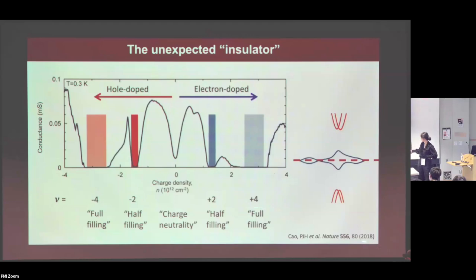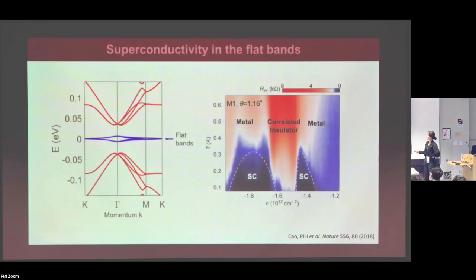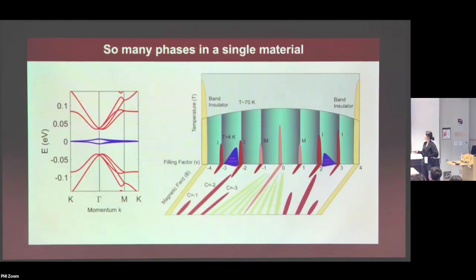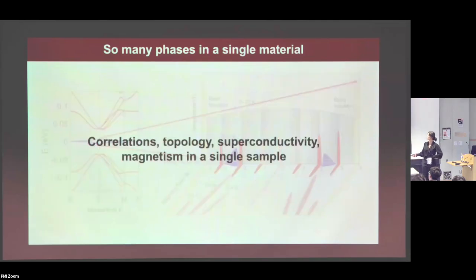But the surprising thing that happened in 2018 was that even when you just half fill this band, where there's no band insulator, you still have this suppressed conductivity, which is the correlated insulator, the insulator gap formed by the strong interactions between the electrons in the flat bands. And in the same material, as you've already heard, there was also superconductivity discovered near this correlated insulator space. And after that, so many different phases were discovered within this single flat band. There's correlated insulator, superconductivity, topological phases, or even magnetic phases as a function of filling factor, temperature, and magnetic field in this system. So the whole point is that you can reach all these different phases just by in situ gating in this single material and single sample.